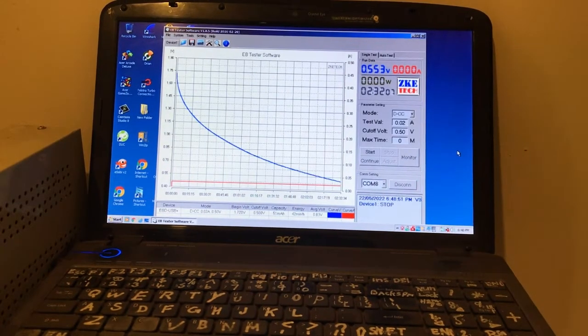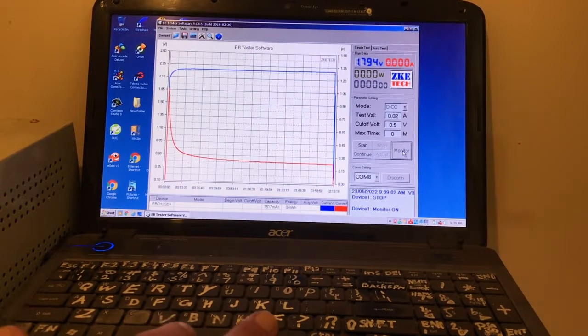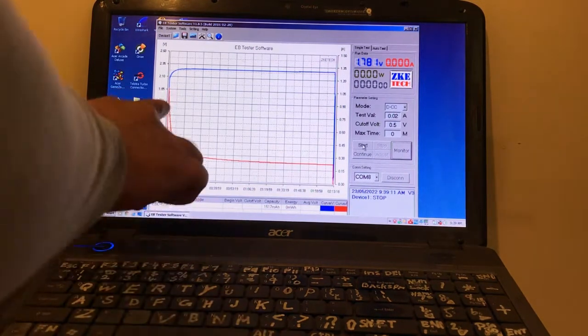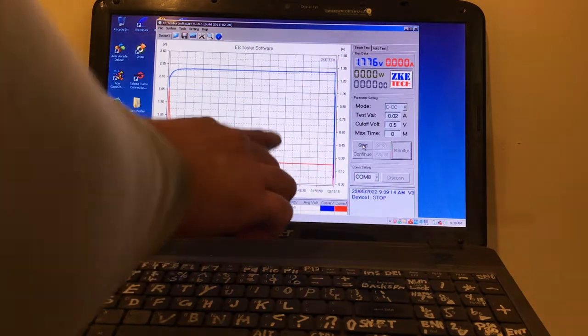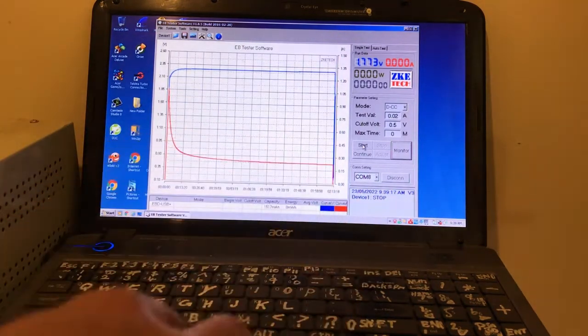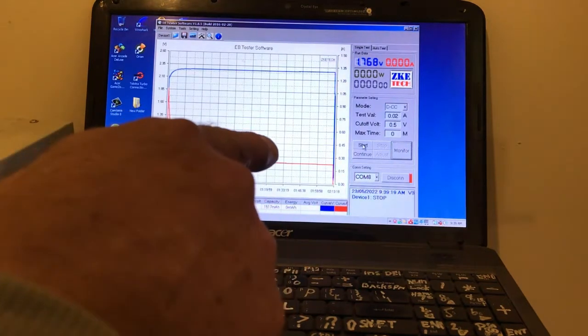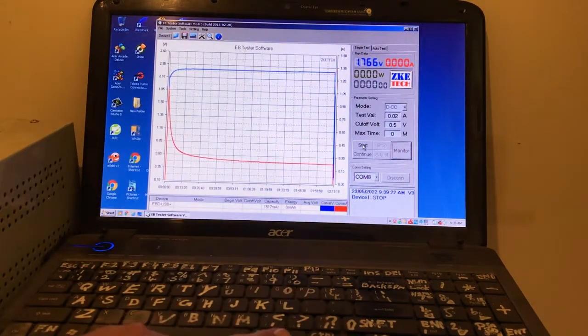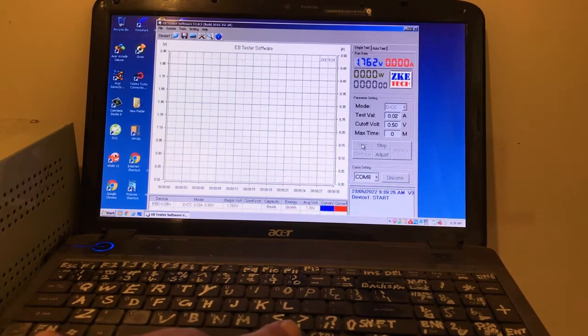First discharge of the cell, 51 milliamp hours, 42 milliwatt hours. Average voltage 0.83. 2 hours and 32 minutes. Okay, it's the second day. Cell's been in electrolyte overnight. It's just had a charge for 2 hours and 13 minutes. It did take an amp and then slowly worked its way down to about 200 milliamps, starting 20 milliamps now.